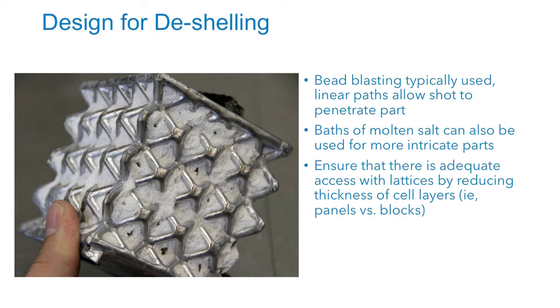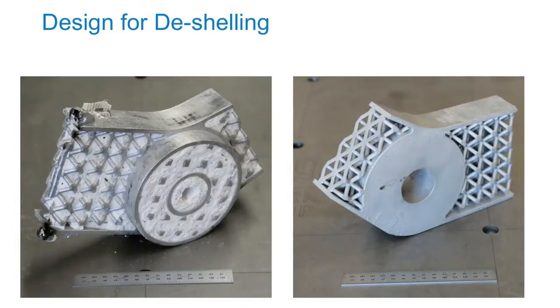That being said, there are some exceptions to the rule. You can also pay a lot of money and have your part thrown in a bath of molten salt that will actually dissolve the ceramic, but that adds quite a bit of lead time and cost. So generally we found sticking to 1 or 2 layers of unit cells is a pretty good rule of thumb, and also abiding by those negative feature and positive feature rules to make sure that your positive features are going to withstand the whole process, and that your negative features allow for full shell buildup.